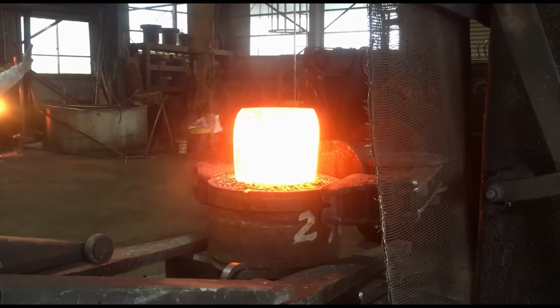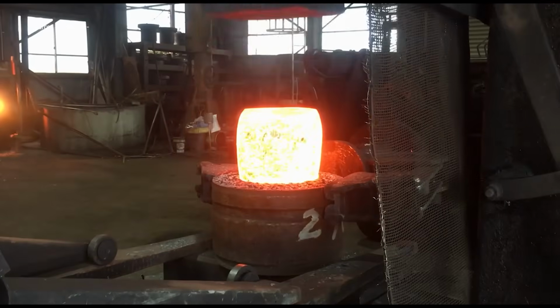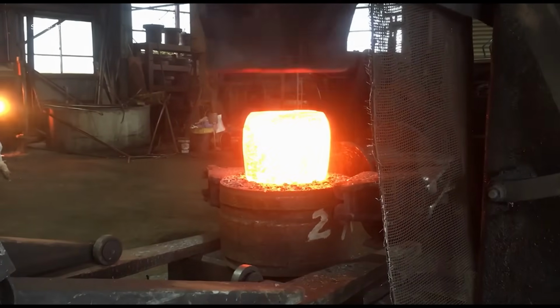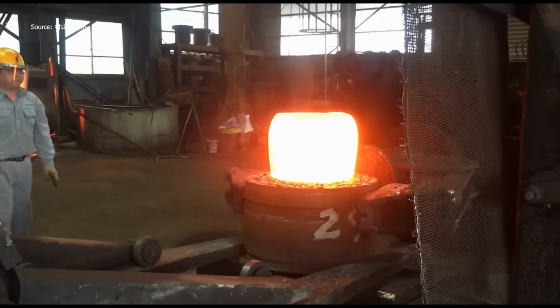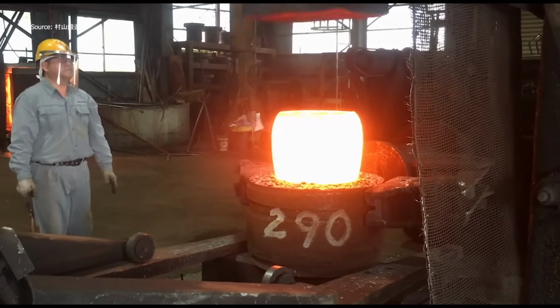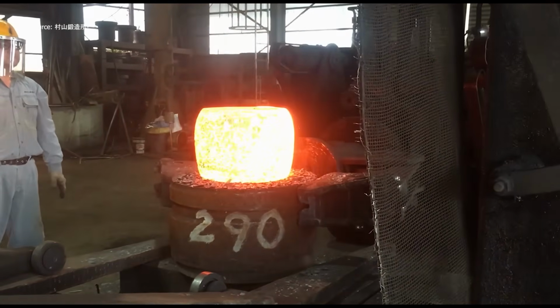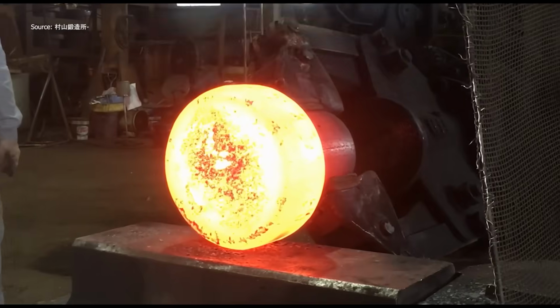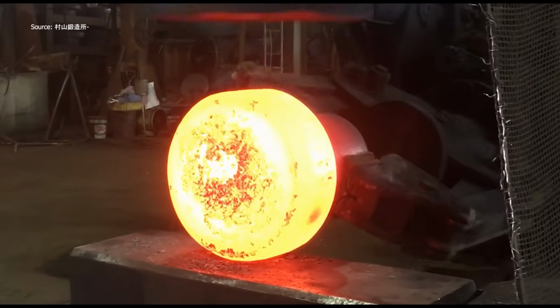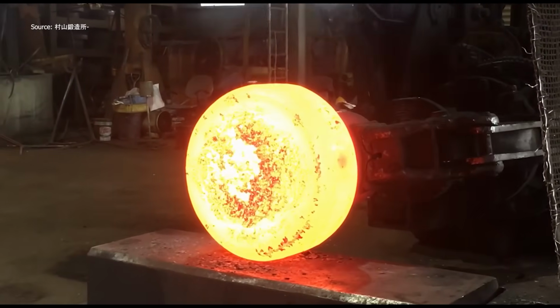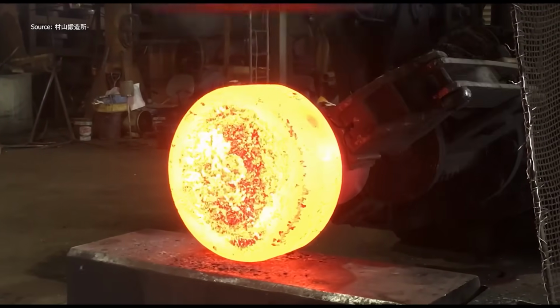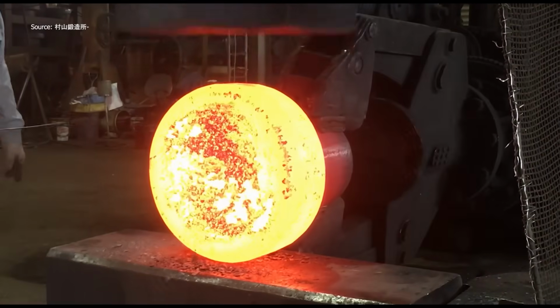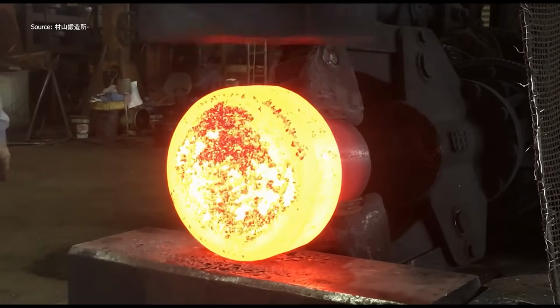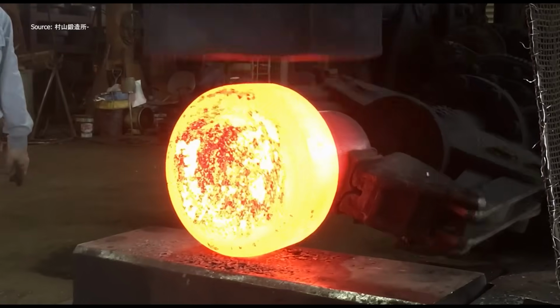At this stage, both sound and color guide the operator more than sensors or screens. First, the surface scale is removed, allowing clean contact with each blow. Then the shaping begins. The hammer compresses the billet, gradually forming the cylindrical body. Forging direction alternates in stages to ensure balanced internal grain flow. Height and symmetry are monitored continuously, adjusted by eye and with calipers.